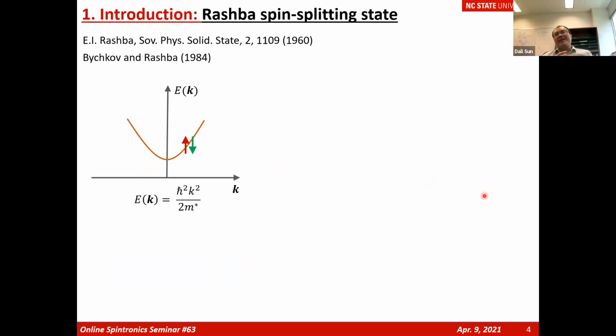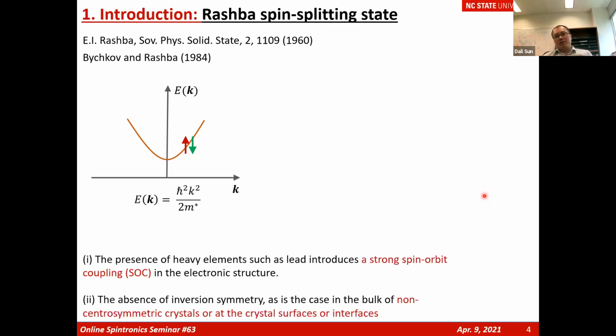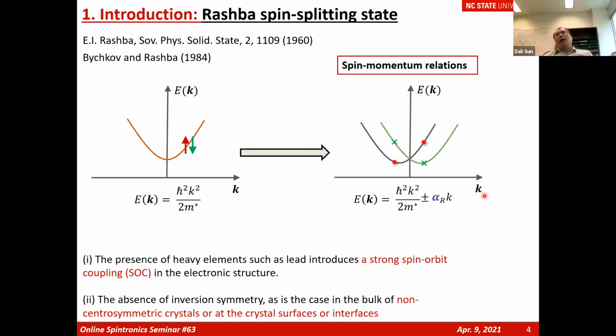I guess everyone here belongs to the spintronics community. So the Rashba effect is pretty well known, a typical spin-dependent feature in crystals. If a crystal possesses a large spin-orbit coupling and lacks inversion symmetry, like in a bulk non-centrosymmetric crystal or at an interface, it will introduce a splitting of the 2 spin bands towards opposite directions in k space, holding different spin polarizations with opposite k values, indicating spin-momentum locking.